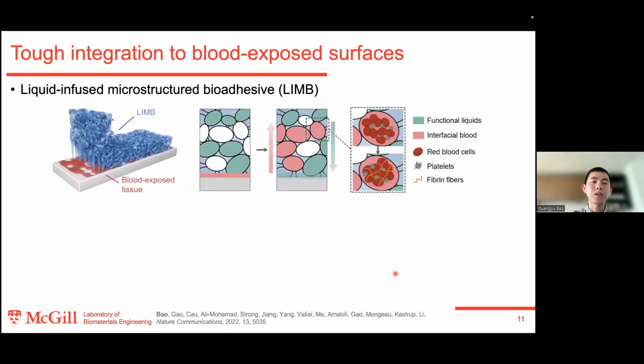So to overcome this challenge, we have created a hydrogel called liquid-infused microstructured bioadhesives. Based on the tough hydrogel matrix that we developed before, we use freeze drying to make the matrix porous and dry. We fill this porous and dry matrix partially with the adhesive liquid while leaving some of the pores open. When this type of bioadhesive is attached to the blood-covered tissue surface, the blood can be quickly absorbed through capillary suction by the empty pores. At the same time, the matrix will deliver the adhesive functional liquid to the interface to facilitate the integration.